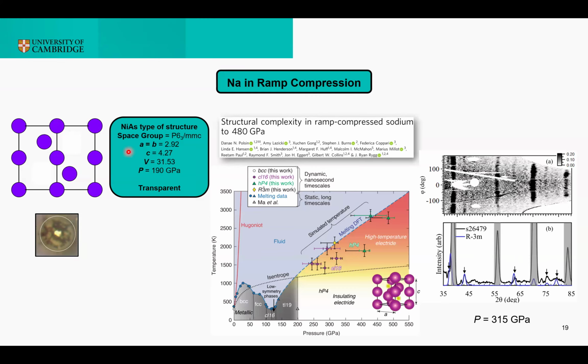The second example I want to show is based on a ramp compression experiment. Here I'm showing the high pressure phase of sodium, called sodium HP4. This phase is particularly interesting because it becomes transparent at more or less 200 gigapascal. And studying this type of exotic system is of great interest to understand the behavior of simple elements at non-ambient conditions. That was what motivated our collaborators at the University of Rochester to study the behavior of this element in a ramp compression. Together with sodium HP4, this study identified an additional phase here at 315 gigapascal that was indexed as R3̄M, for which I reported the experimental data here.